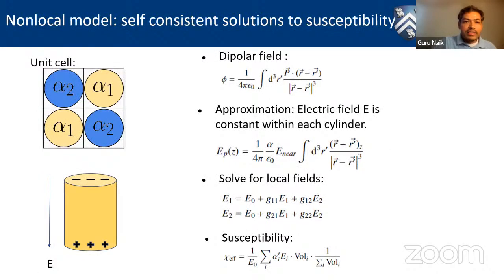Okay, so the way we handle this is a self-consistent solution to the susceptibility. You solve for local fields and global fields. The applied field is E0, and then the local field is E1 in domain 1 and E2 in domain 2. So we need to solve for the fields in these domains and then get the effective susceptibility, which should be dependent on the angle of incidence, or K of the incident light. So that's what we are currently working on. We're still benchmarking our model, and I don't have the results applied to tantalum disulfide yet, but that's where we are heading towards.